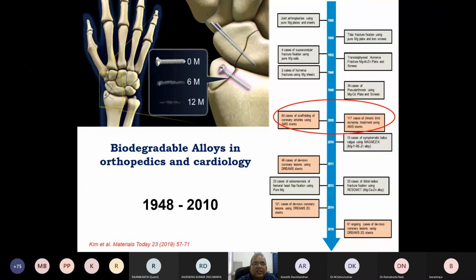You know the metal rods and so on that we are using, but now there is a concept: can we develop biodegradable alloys? Because whatever biomimetic material you develop, it is very difficult to beat the metals. But metals have the problem of density, weight, and then the Young's modulus. So can we develop a biodegradable metallic implant that biodegrades itself in the body after completing the healing? And most of you are from metallurgy, you know that magnesium is one of the candidates for such implants. But magnesium is highly reactive, very difficult. It goes away within no time in an aqueous or biological environment.